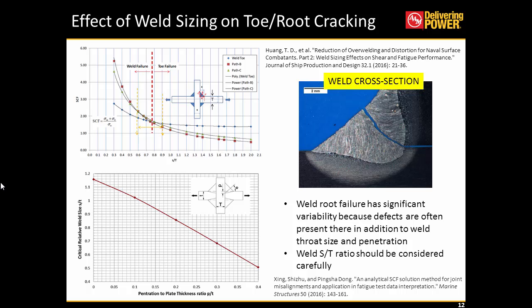So there are three lines. If you can see, if the S by t ratio is greater than, in this case, 0.8, we see that it can be toe failure. And if it is less than that, it's highly likely it can be a weld failure. Weld failure can be root or throat fracture. On the right-hand side, we show a case, which we'll discuss in a later slide, where we had a throat failure.